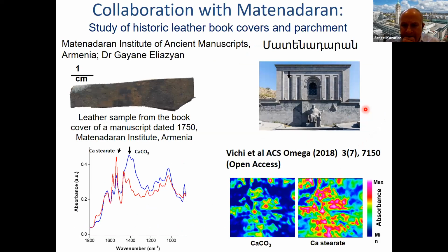I also would like to show you just one result. It was a recent collaboration with the Institute of Ancient Manuscripts in Armenia. It's one of the largest depositories in the world, particularly for Armenian manuscripts, of course. And there was degradation of ancient manuscripts because of leather. And we were able to detect in these samples also the formation of calcium stearates.